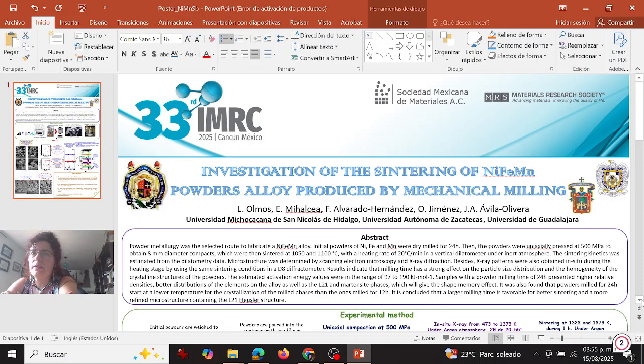The sintering kinetics was estimated from the dilatometry data. Microstructure was determined by scanning electron microscopy and X-ray diffraction. Besides, X-ray patterns were also obtained in situ during the heating stage by using the same sintering conditions in a D8 diffractometer. The result indicates that milling time has a strong effect on the particle size distribution and the homogeneity of the crystalline structures of the powders. The estimated activation energy values were in the range of 97 to 190 kilojoules per mole.